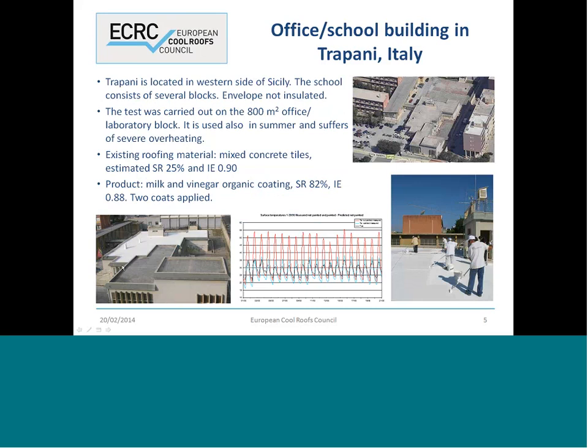The treated surface was about 800 square meters, and the original roof system was made of concrete tiles with an estimated solar reflectance of 25% and infrared emissivity of 0.9. The cool roof application consists of a milk and vinegar-based elastomeric coating. Measured solar reflectance was 82% and measured emissivity 0.88. Two coats were applied on the roof as inferred from this photo here on the right.